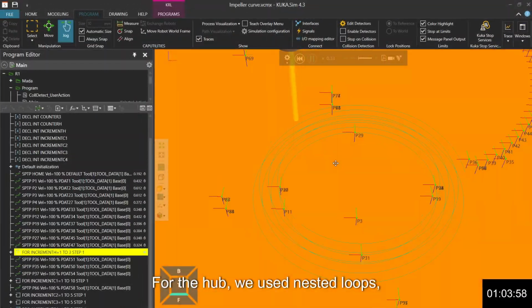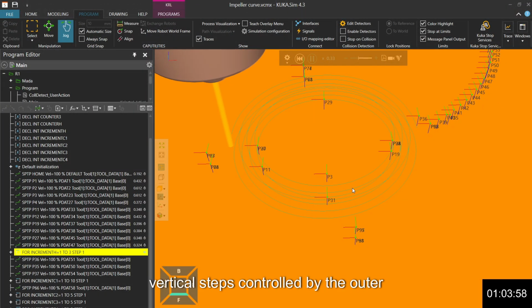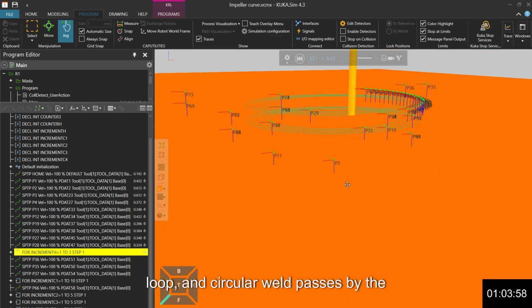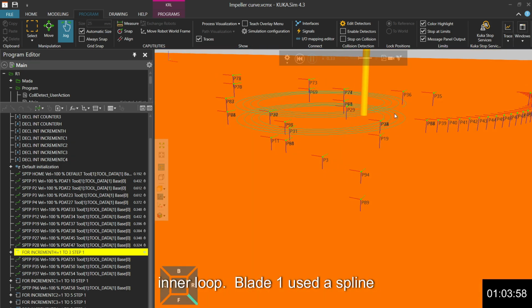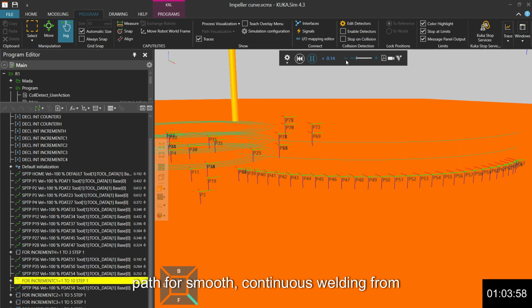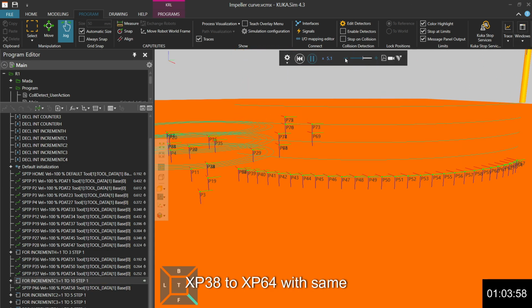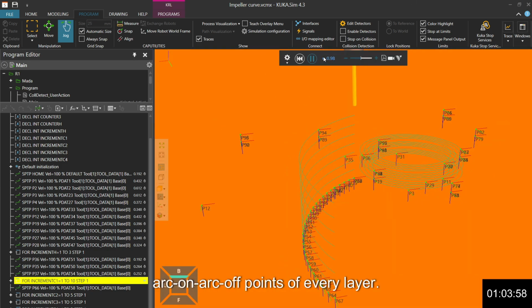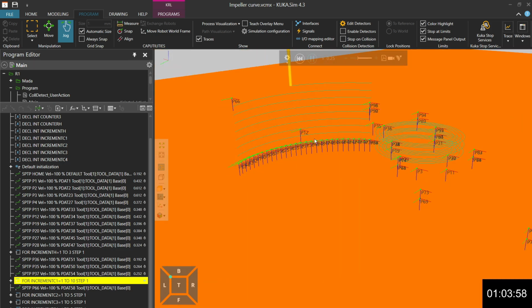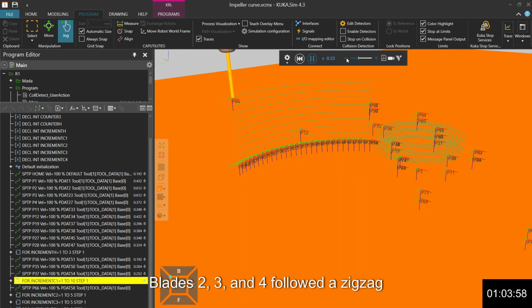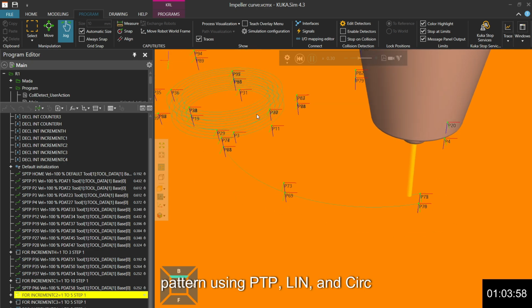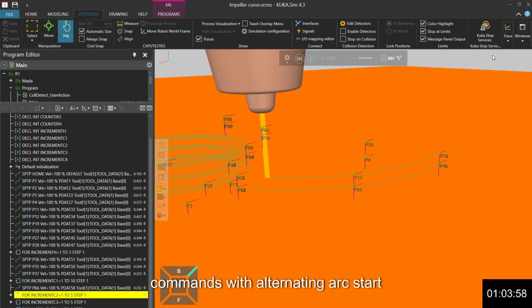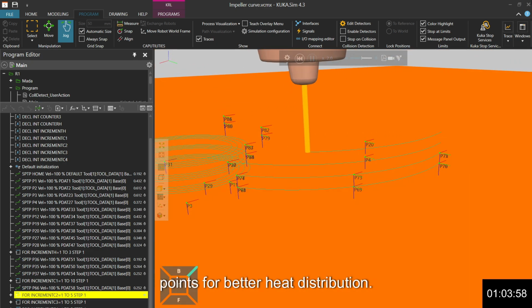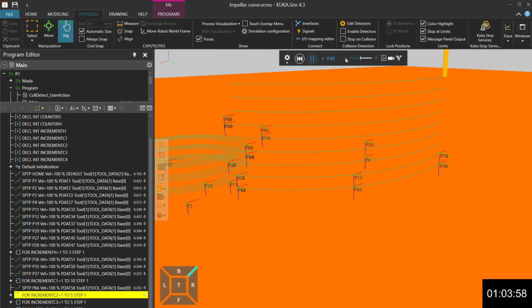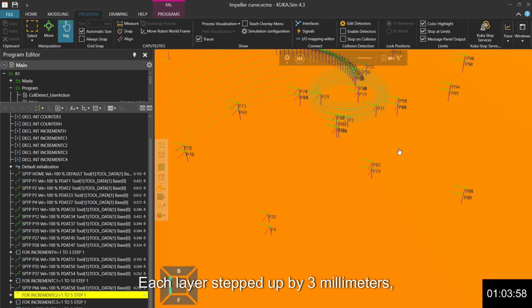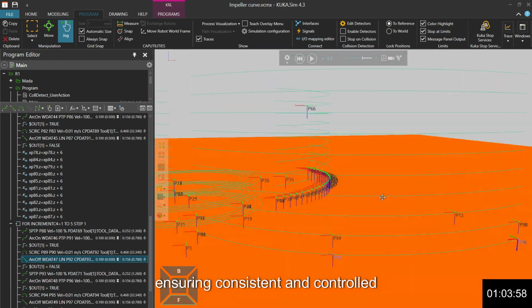For the hub, we used nested loops, vertical steps controlled by the outer loop, and circular weld passes by the inner loop. Blade 1 used a spline path for smooth, continuous welding from XP38 to XP64, with same arc-on arc-off points of every layer. Blades 2, 3, and 4 followed a zigzag pattern using PTP, LIN, and circ commands, with alternating arc start points for better heat distribution. Each layer stepped up by 3 mm, ensuring consistent and controlled vertical buildup.